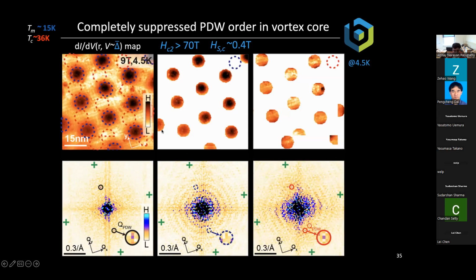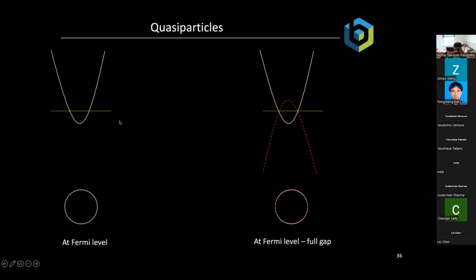And so the point, I could have just made this point just by asking you to look at this image. The point that I want to make is that these modulations are gone inside the vortex. And so they're intimately related to the presence of the uniform superconductor. And therefore, the important point that I want to make is that this modulated superconductivity really requires both superconductivity and magnetism in order to exist. So it's some property that's an interaction between superconductivity and magnetism.